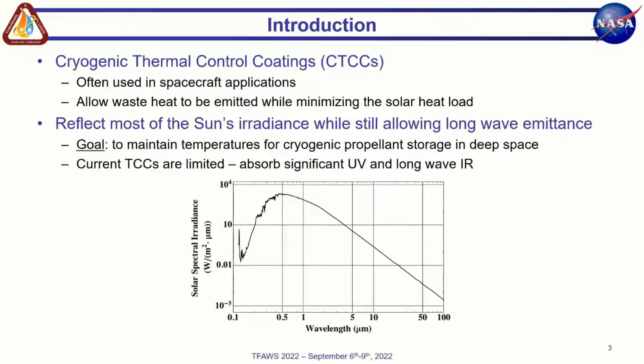So cryogenic thermal control coatings are often used in spacecraft applications, and they're used to provide thermal control of the spacecraft. The plot at the bottom shows the sun's spectral radiance over a given wavelength. You can see that it starts to become significant at about 0.2 microns, out to about 10 microns. The objective of the project that we're presenting today is to develop a cryogenic thermal control coating that can maintain temperatures for cryogenic propellant storage in deep space. In order to do that, it's important for the coating to reflect most of the sun's irradiance while still allowing long wave emittance. Current thermal control coatings are limited because they absorb significant UV and long wave infrared.